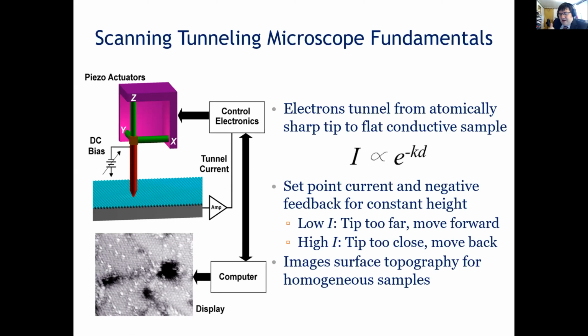We can use that in a feedback loop to get a constant height of the probe above the surface. If the current's too low, that means the tip's too far away and we move it forward. That increases the current. If the current's too high, that means the tip's too close and we move it back. That decreases the current. And so if you do that and then move your probe along the surface, you'll get the probe tip a constant distance away from your surface without touching it. You can image surface topography as long as you have a homogeneous sample. And there's an image there in the bottom left that's an example STM image.